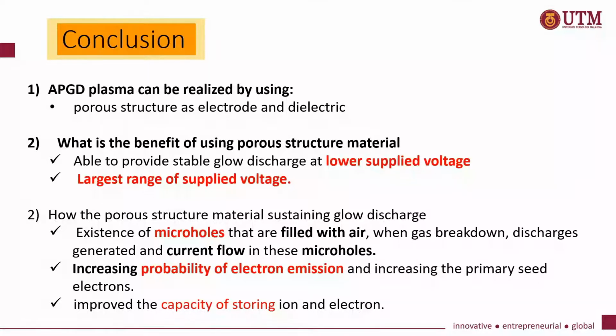Also, the porous structure material contains pores of micron size, which will produce a hollow cathode effect and enhance the glow discharge plasma. Also, because of the existence of the micro-holes that are filled with air, when the gas breaks down, the discharge will be generated and the current flowing through the microchannels in these micro-holes will increase the probability of electron emission and also increase the primary seed electrons.